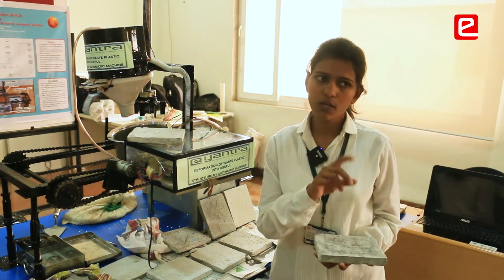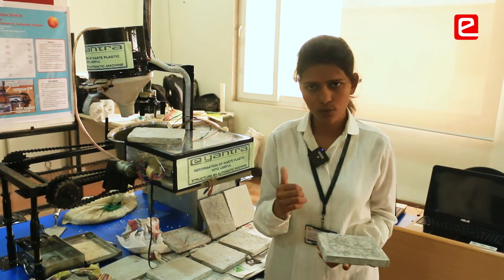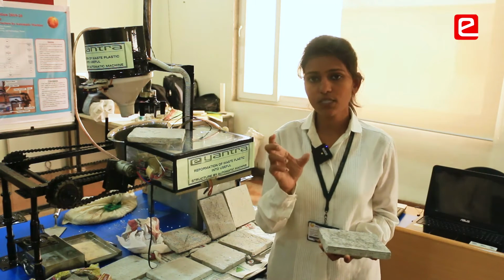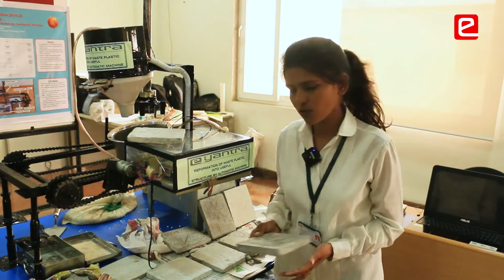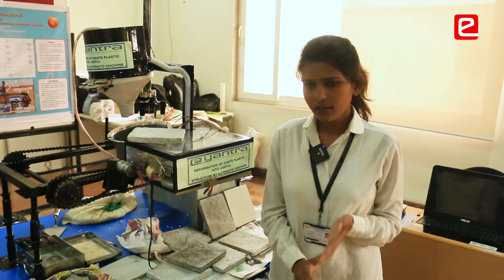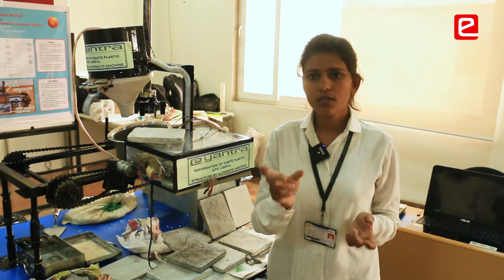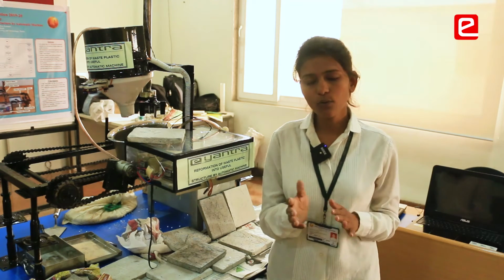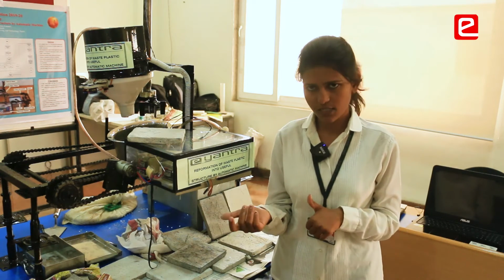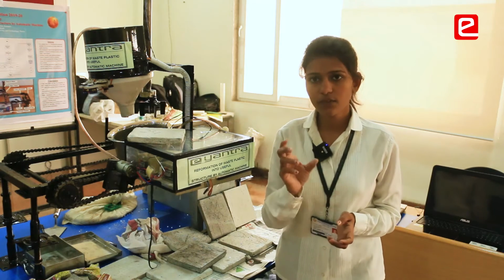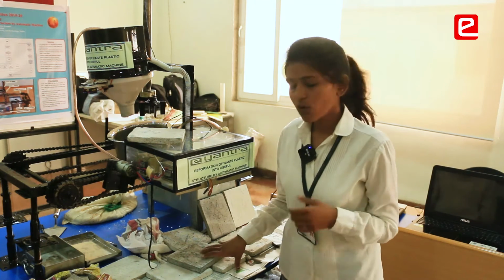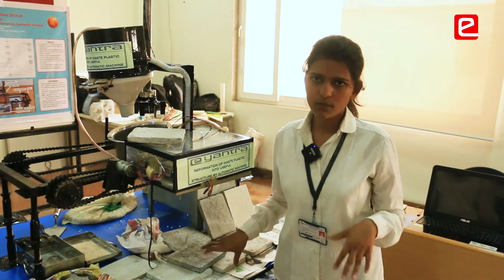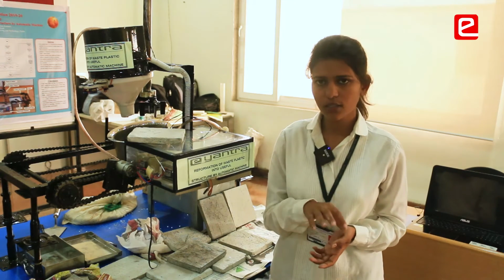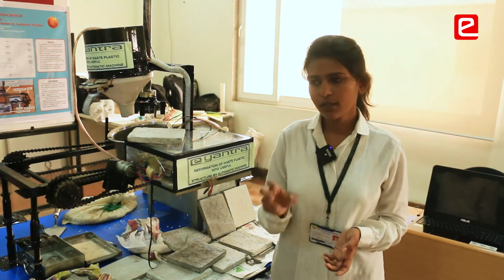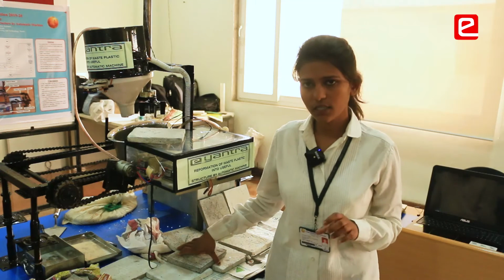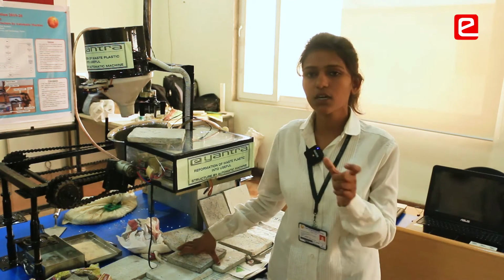After that, we take it out and calculate the weight of the slab. We use the formula (W2 minus W1) upon W1 into 100 to calculate the percentage of water absorption, where W1 is the weight of the dry slab and W2 is the weight of the wet slab. In the ordinary existing slab, the percentage of water absorption is 12%. But in our slab, water absorption is 2.9%, which is within the limit.